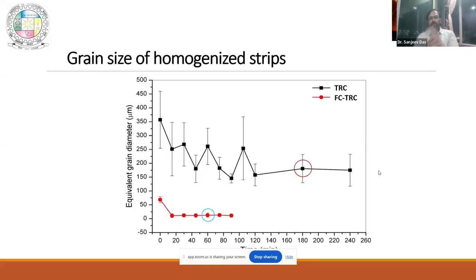In the next one, this is the complete cycle of how you are homogenizing these strips. And you will see that for TRC, it is very random, very big grains. But for forced convection, after 15 minutes, you can get a very equiaxed, fine grain structure, and it stays constant, right? Now the thing is, why does this happen?